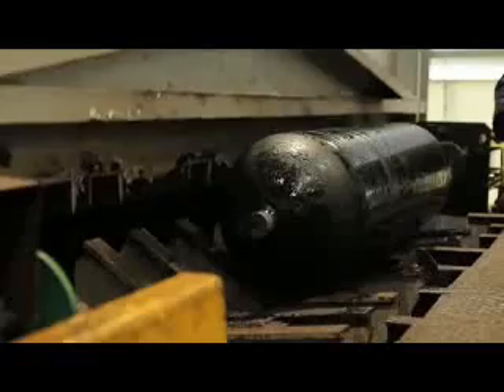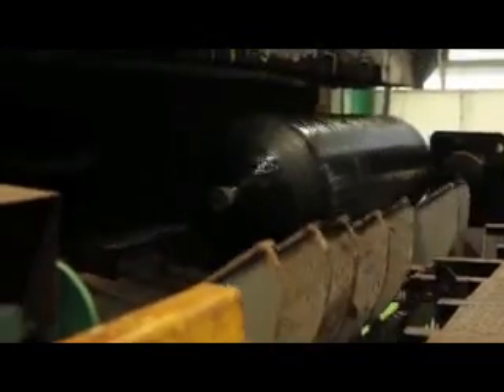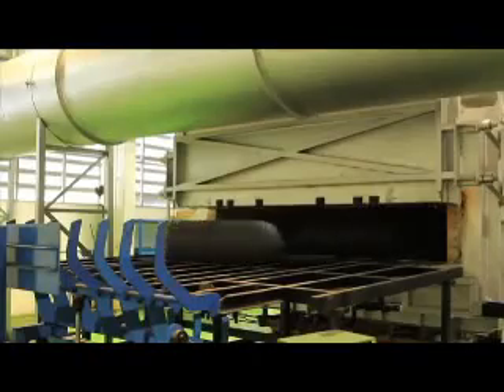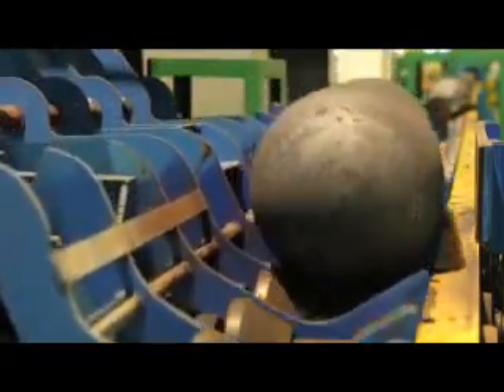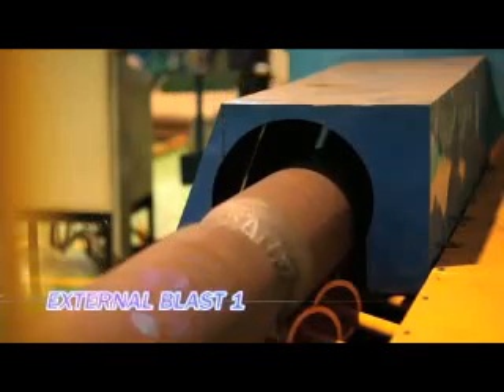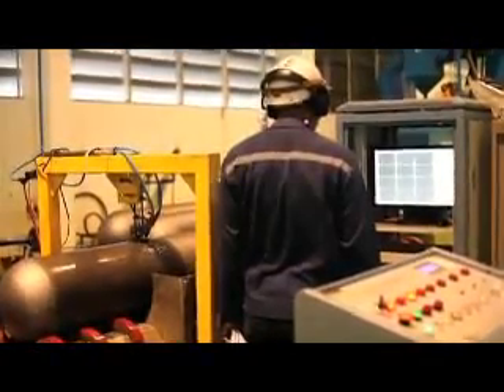Two, quenching process to steam and hard coat with chemicals mixed with water for 3 minutes. The water temperature must be between 30 to 40 degrees Celsius. Three, tempering process to steam and release tension of the tank by heating around the body at a temperature of 590 degrees Celsius for more than 90 minutes. External blast 1: removing the scale and rust from the external surface of the cylinder. Ultrasonic test: inspect the defects of the cylinder by ultrasonic.